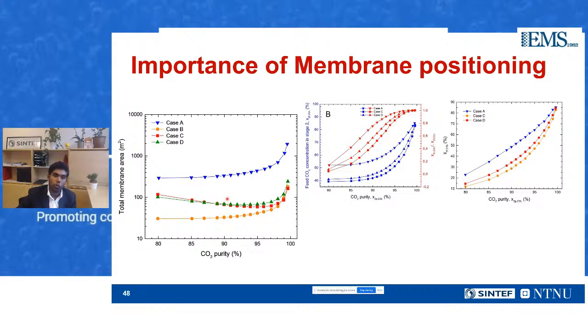And we wanted to see how the first stage has purified the CO2, which is on the x-axis. On the y-axis, you see the feed CO2 concentration that goes into the second stage, which is basically the permeate CO2 concentration of the first stage. So here, when you have a membrane of very high selectivity on the first stage, then you have higher CO2 concentration, which is case A. So in the sense that when you have case A, you have a higher CO2 concentration, which means that the membrane on the second stage is forced to operate at a higher CO2 concentration than in the case where you're using a membrane with a high permeance but a lower selectivity.